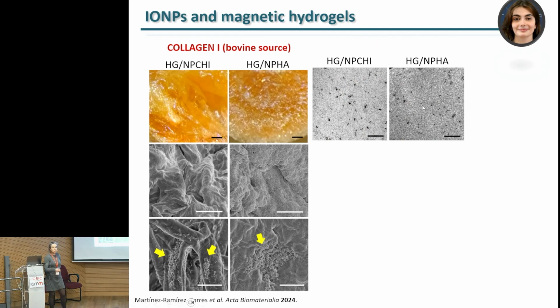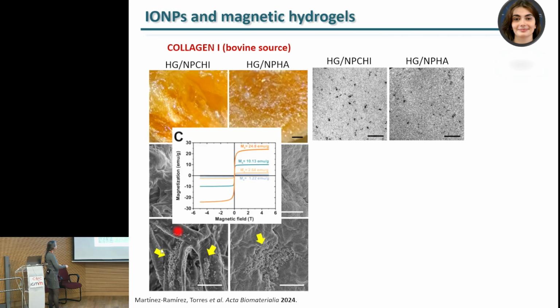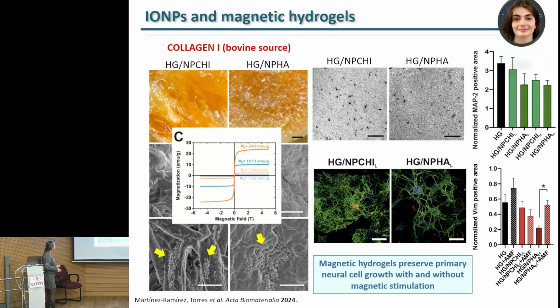We did transmission electron microscopy to prove that they were not just in groups in certain areas of the hydrogel, but homogeneously dispersed throughout the matrix. Again, we demonstrated the incorporation of those magnetic properties into the hydrogels because of the incorporation of the iron oxide nanoparticles. You see here the magnetization that was indeed dependent on the dose of the iron oxide nanoparticles loading. And then again, we cultured neural cells on top of this, and we proved that the neurons differentiated into mature neurons without troubles, and we had an important effect of the application of an alternating magnetic field on the differentiation of glial cells from this culture.